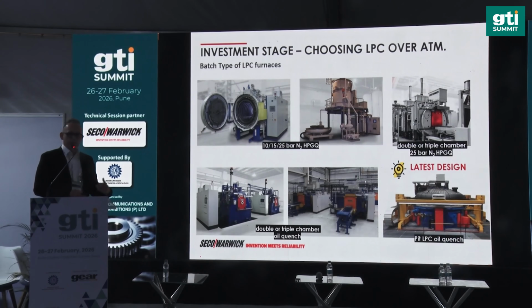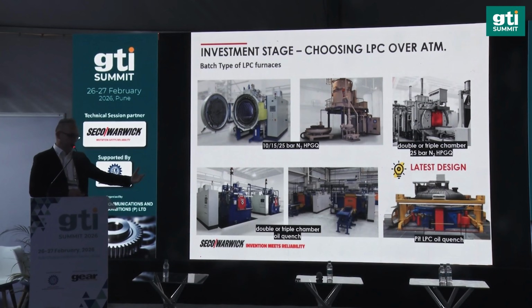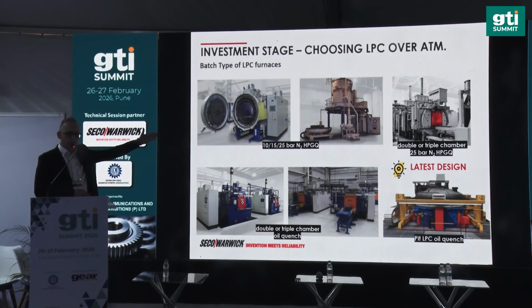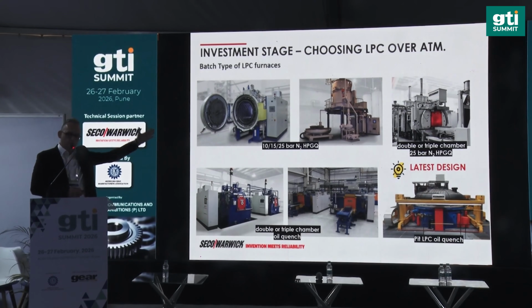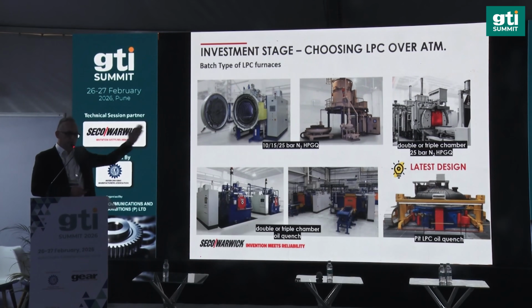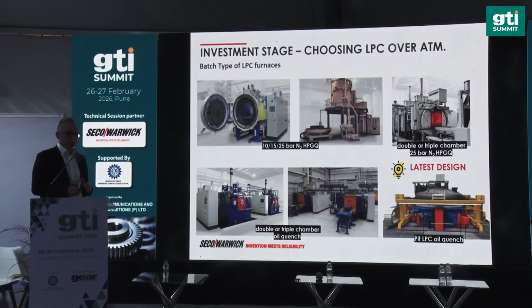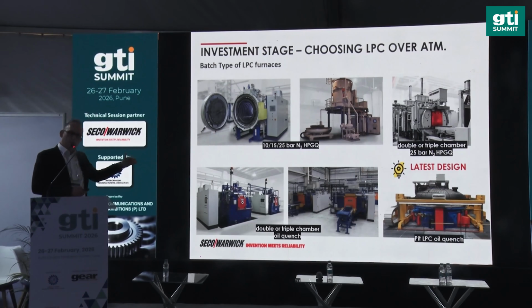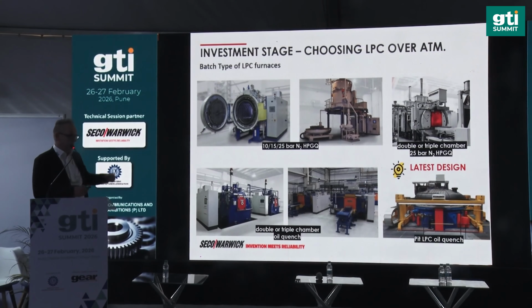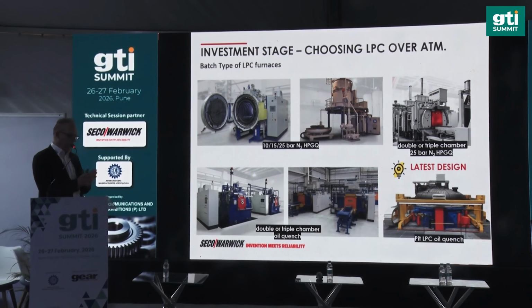What about the equipment? There are so many of these. As it was said, depending on where you are, what your application is, what your approach is, we may offer you different solutions. That means for some of you, single chamber furnaces with high pressure gas quenching, either horizontal or vertical, might be the key point. But for others, due to other aspects, multi-chamber systems with high pressure gas quenching might be the right solution. However, in many cases you cannot go with high pressure gas quenching, therefore you have to transition into an oil quenching situation, where we have a very smooth transition from traditional technology utilizing oil quenching into vacuum carburizing utilizing oil quenching.